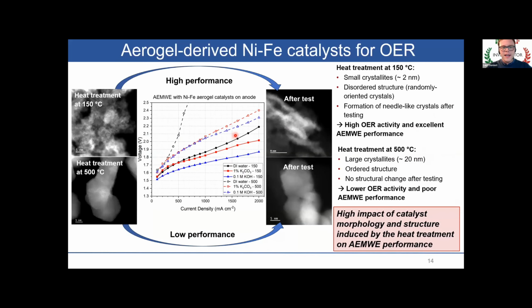After testing in a water electrolyzer and characterizing the material before and after the test, we noticed that this aerogel heat treated at low temperature showed a disordered structure with randomly oriented small crystallites of the size of about 2 nanometers, which after testing changed their morphology to form needle-like crystals, while the catalysts that have a low activity, like commercial materials or catalysts treated at high temperature, show larger crystallites that do not undergo structural modification after testing.